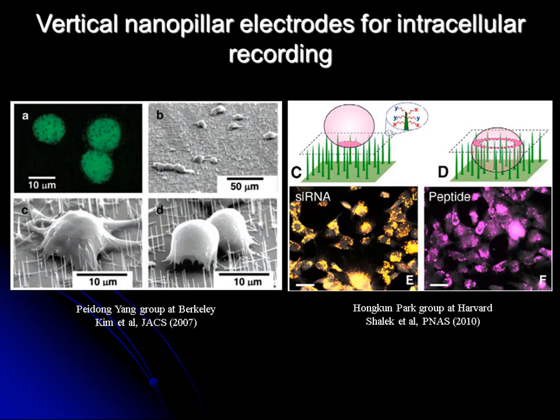When my lab started a few years ago, we noticed two beautiful works. One is the work from Peidong Yang's group at Berkeley. They showed that you can culture cells on vertical nanoneedles, very sharp needles about 100 nanometers in diameter. It looks very painful to the cell. However, what Peidong's group reported is that the cells can continue to survive on those vertical nanoneedles. They can divide and survive for a week. A few years later, Hongkun Park's group from Harvard showed that you can use those nanoneedles to deliver fluorescent molecules to the cell. So the hypothesis is when the needle gets very, very small, it can poke into the cell without killing the cell.